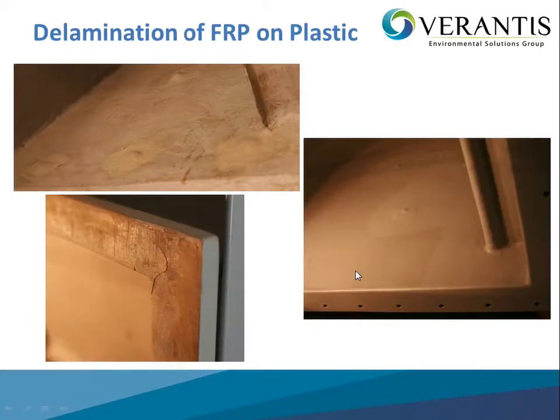So, delamination of FRP on plastic. The left is an example of one of our competitors that fabricated a plastic fan and then overlaid it with FRP in order to market this as an FRP fan. It's very difficult to achieve a strong bond between two different materials, and as you can see, there's a little crack right here and there's one right here where the FRP is already starting to pull away from the plastic. Again, these haven't been used or run in a contaminated area, but that's certainly some points for attack right there.